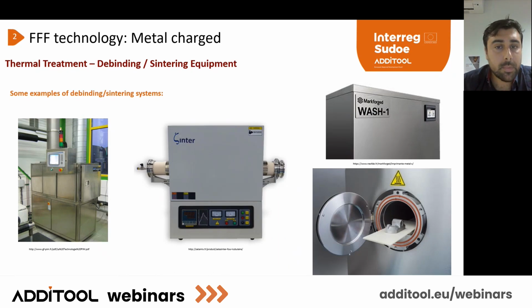Also, you can find on this picture some examples of debinding and sintering systems. This is a pre-debinding oven, an oven for sintering, and what we see here is the oven is cylindrical. This is very important for sintering a part, because in Additool we don't have such an oven. We have the same oven, but in a cubic format, and the cubic format is not adequate for sintering. So the sintering has to be in a cylindrical oven like this.